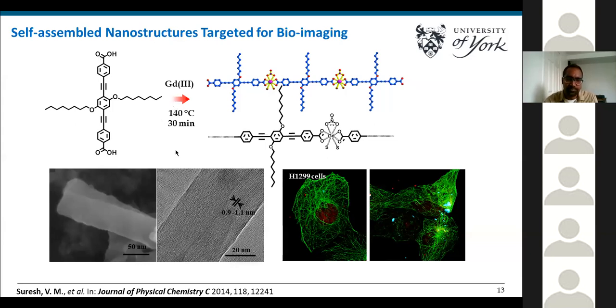Next question comes from Dr. Sangeeta. She asked, very nicely you showed by the competitive reaction that the MOC gels form the preferential structure with the best binder. Will the same thing happen if you add them in a sequential manner? Yeah, that's possible, as long as there is free MOC available in the solution. Initially, if you add a binder with strong binding affinity, it self-assembles with the MOC present in the solution. Now, when you add the next binder, if there is still MOC available in the solution, it can still bind, and we can still see the morphology from it. But the prominent morphology will be that of the binder with the higher binding affinity.